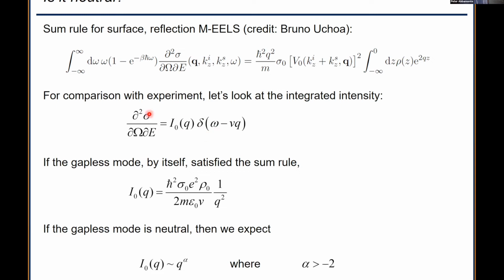And if you take this and plug it into this formula, you can show that I naught goes like 1 over q squared. So what that means is that if this gapless mode was a conventional plasmon and it satisfied the F sum rule, meaning I could write down a partial sum rule just for that mode, then it should go like 1 over q squared. And there's matrix elements and things.